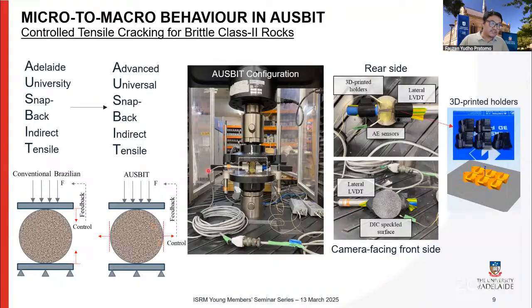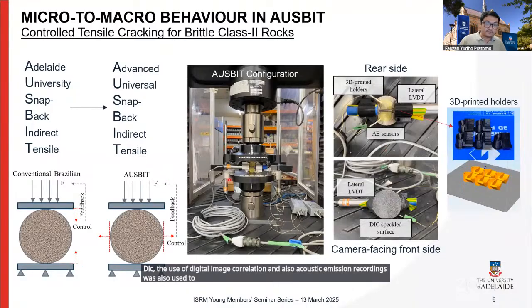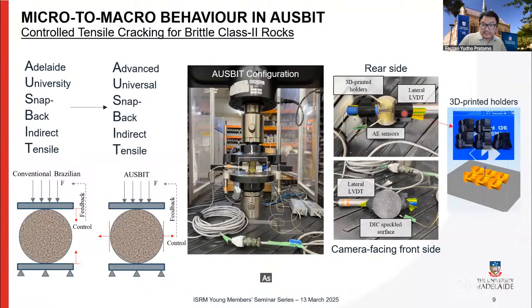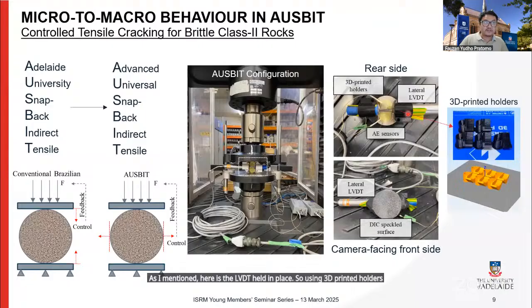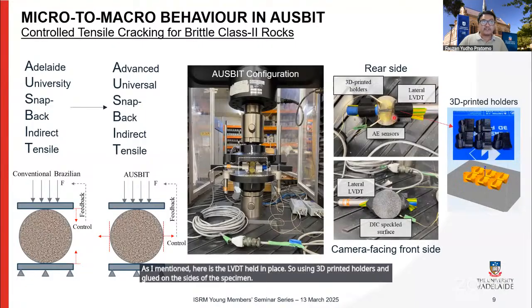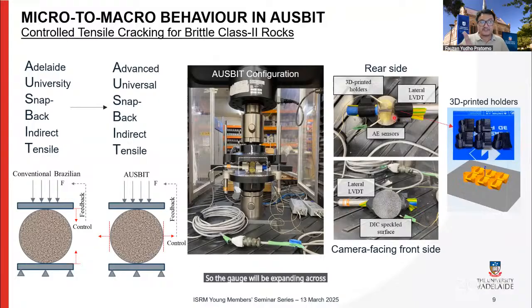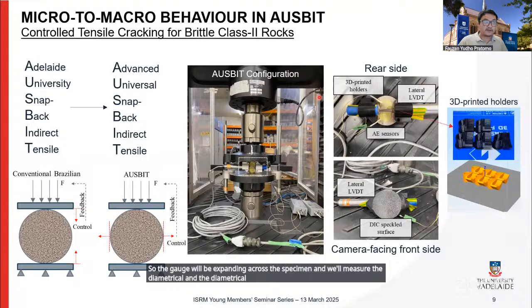DIC, the use of digital image correlation, and also acoustic emission recordings were used to obtain more insights into the fracture behavior. As I mentioned, here is the LVDT held in place using 3D printed holders and glued on the sides of the specimen. So the gauge will be expanding across the specimen and will measure the diametrical extension of the specimen directly.